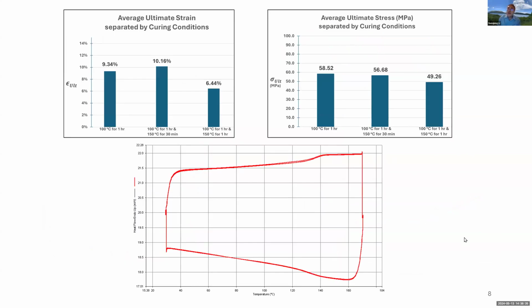All right, once we know this idea works, we want to find more polymers and see if we can have higher energy storage and energy output. So here we show you one of the polymers. For this polymer, we use different curing conditions. Let's say 100 degrees Celsius for 1 hour, 1 hour plus 150 for 30 minutes, 100 degrees for 1 hour, 150 for 1 hour.